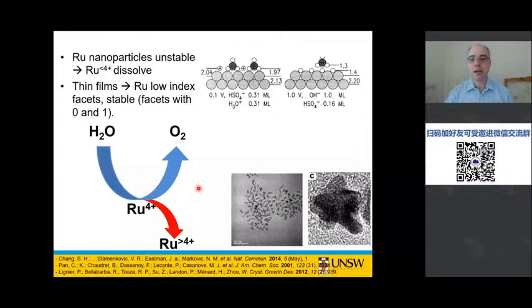So in terms of making ruthenium nanoparticles, which have these low index facets, which we hoped would be stable for OER, synthetically, it's actually quite a challenge, which is great, because the types of ruthenium nanoparticles that really people have managed to make before, these are just a couple of examples from the literature. But as you see, you don't really have much faceting, and you certainly don't have a lot of kind of stable low index facets.